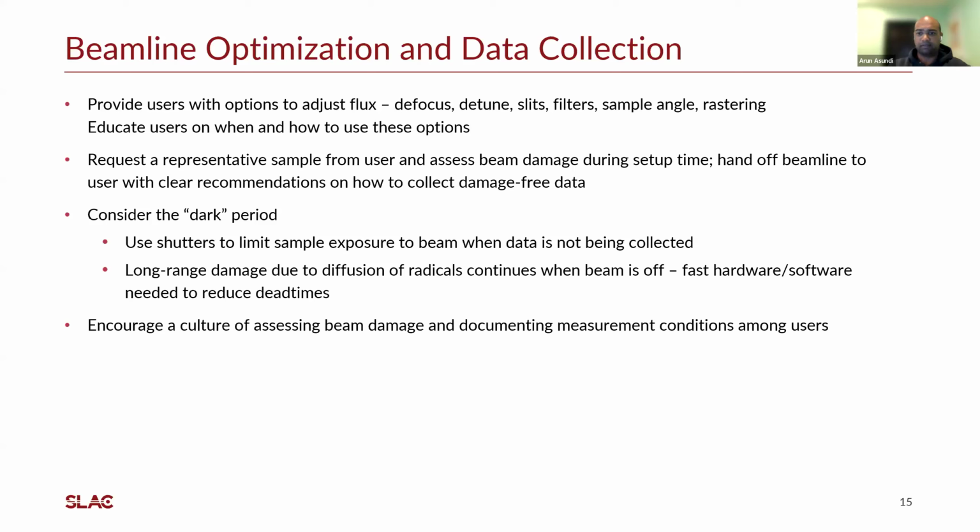Yeah, so in the soft X-ray, the absorption cross section is higher, and so the sample tends to be more susceptible to beam damage under those conditions because more of those photons are absorbed. I don't know if there's a correlation to the mechanism of beam damage. There can be a correlation depending on if different types of detection methods are used for the soft X-ray. For instance, doing an electron yield measurement versus doing a transmission spectroscopy measurement in the hard X-ray regime.